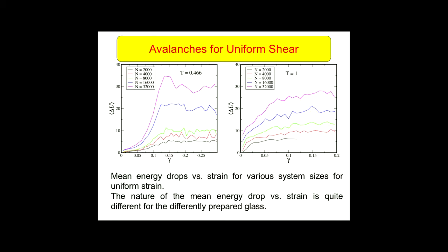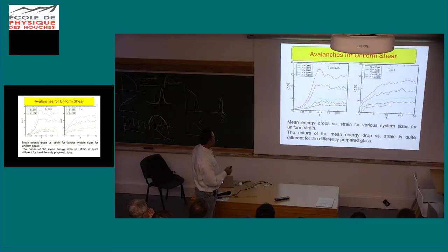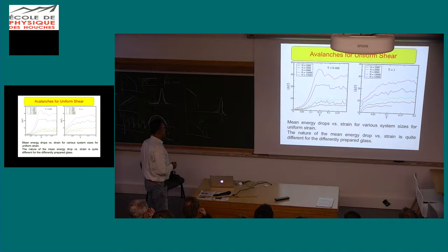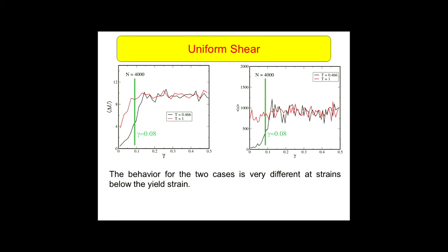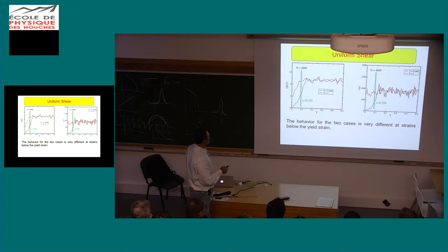Now, comparison with uniform shear. This is not the best. We didn't study this very thoroughly, but basically to illustrate the point that for the poorly annealed glass and the well annealed glass, the energy drops look very different. If I look at the two different initial conditions, they look very different.